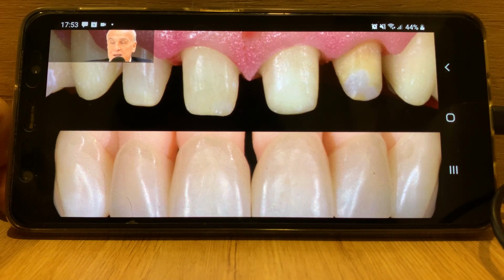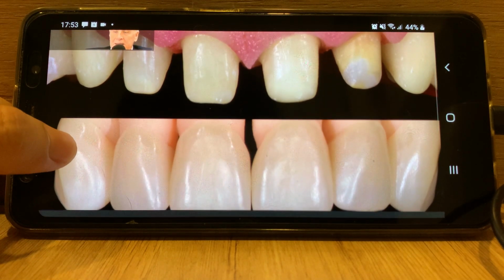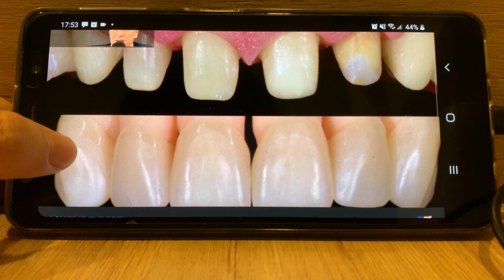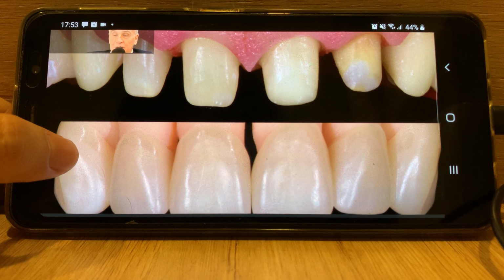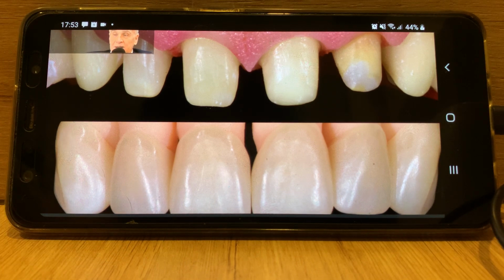This was the same as I showed you before. This is MT multi. This is a material that's a more translucent zirconia. In fact, two types of zirconia. It's rather minimally prepped, although you do need adequate preparation for this. And this was a compromise. We could have used lithium disilicate in this case to make it a little bit more aesthetic. But as you'll see in a minute, why we chose this rather structurally stronger material.